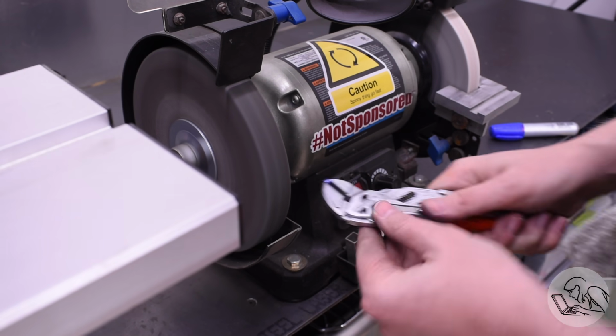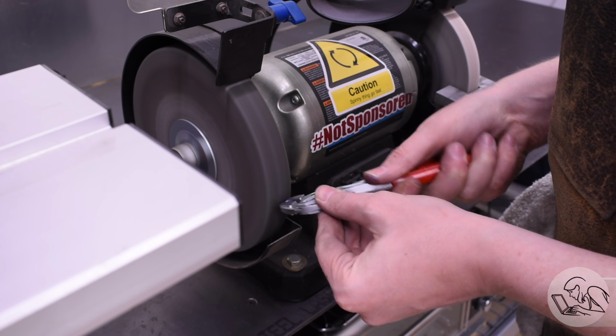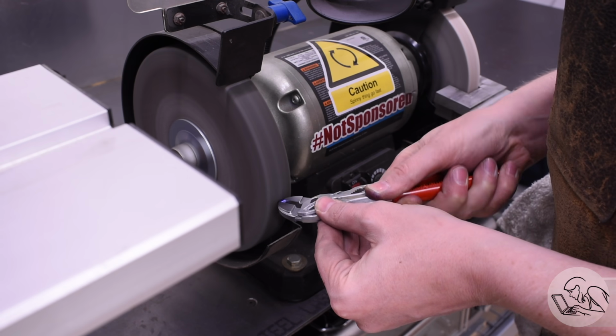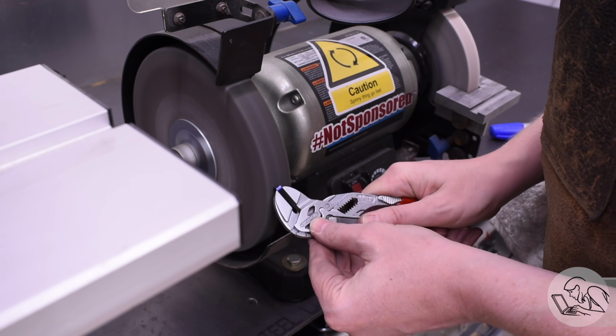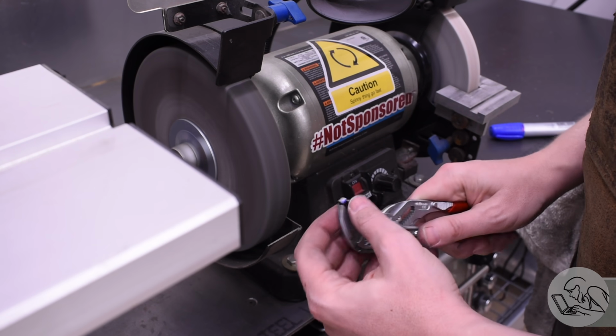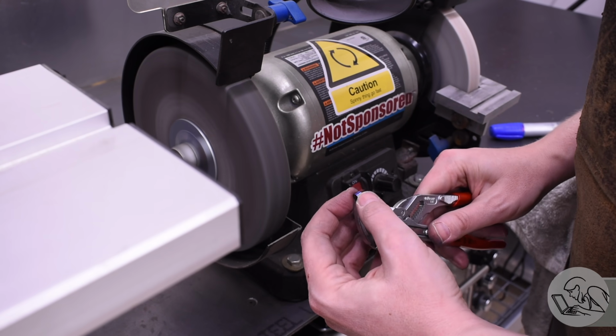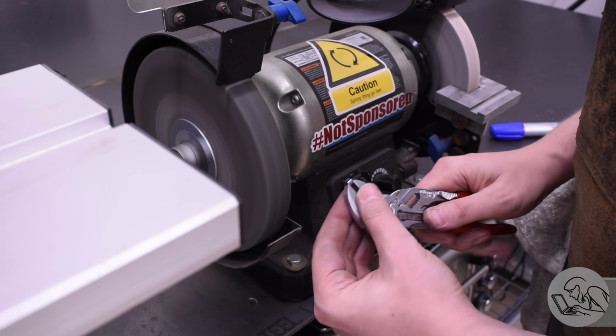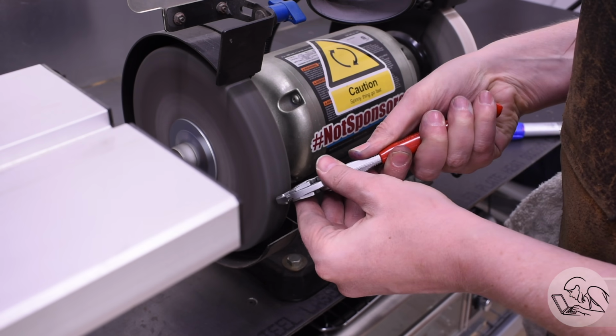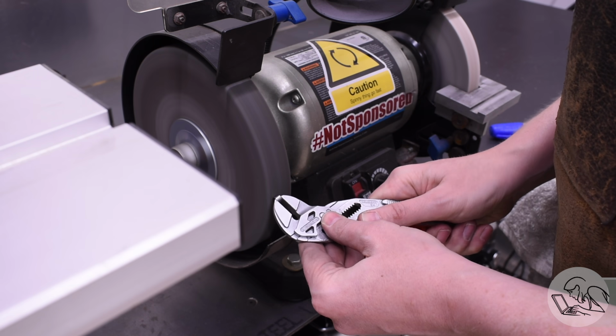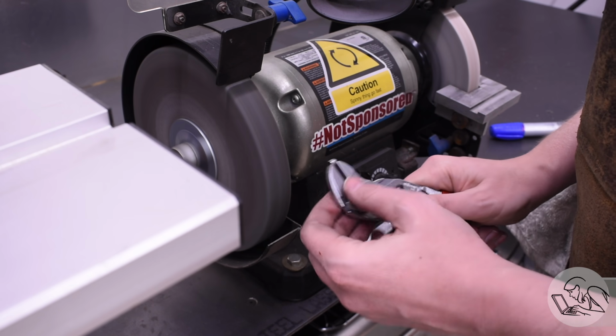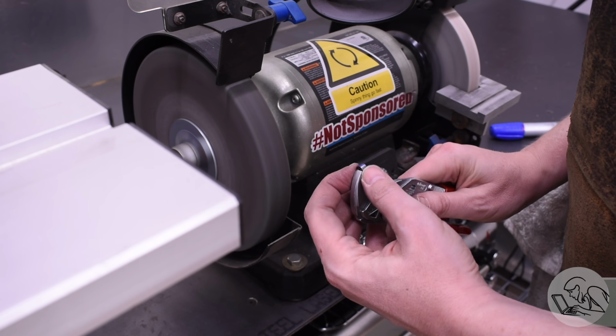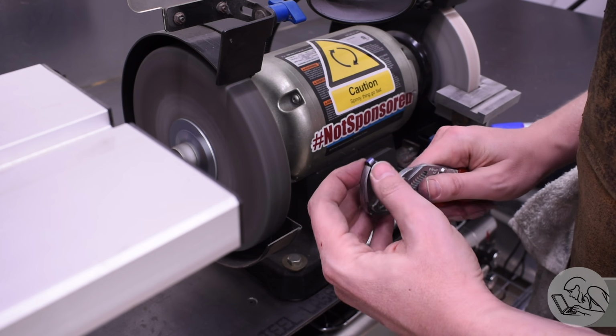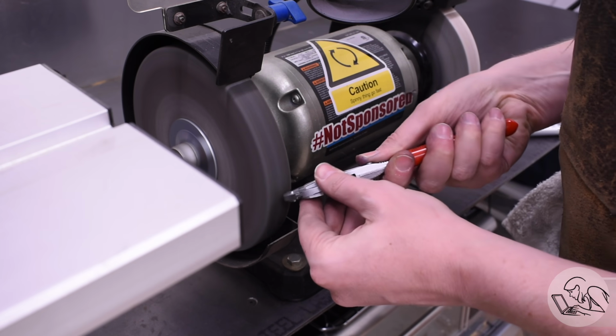That's why if you're making precision tooling like gauge blocks and 123 blocks, you machine them a little bit oversized, then heat treat them, and then surface grind them to final dimension. However, here in the poor person's shop, we can just hit it with the Scotch-Brite a little bit and bring that down to dimension. This doesn't have to be absolutely perfectly round again, it just has to be a nice fit in that hole. The amount that it expanded from the heat treat is well within Scotch-Brite polishing range.